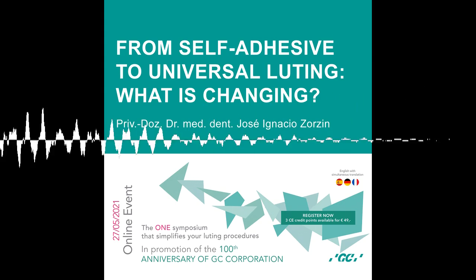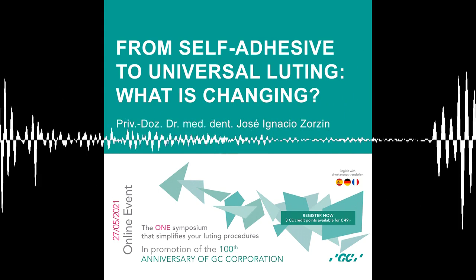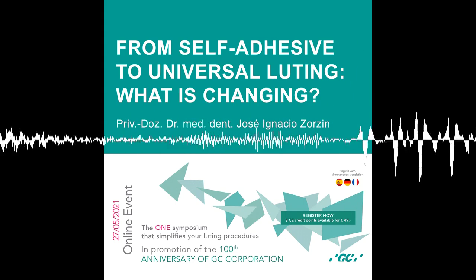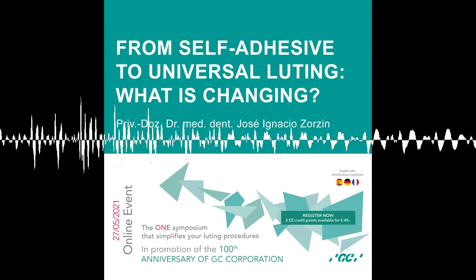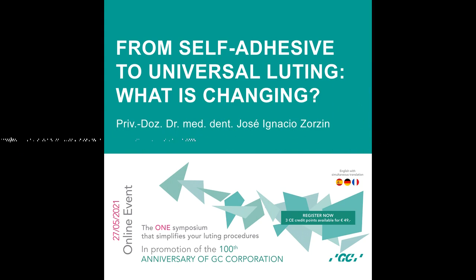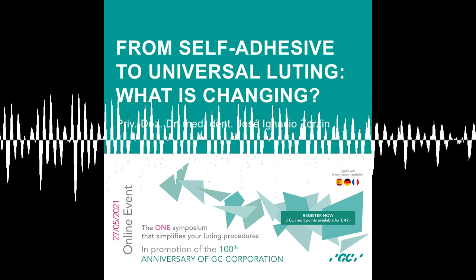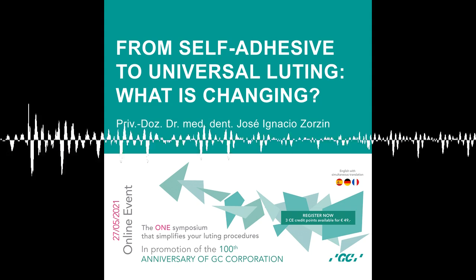But you have other situations where your material is not that translucent. Of course, then you have to rely on the dark cure system of the luting resin. There's a big point: the chemistry inside there has to be very finely balanced to start and to make a good conversion. So whenever possible, take both worlds, take light and take the other. So dual curing whenever possible.